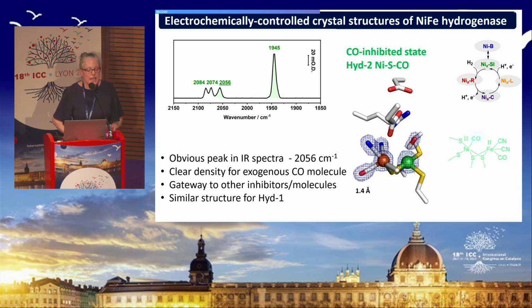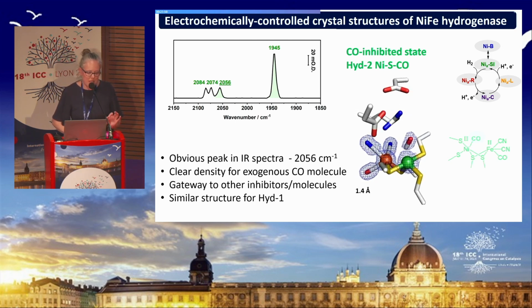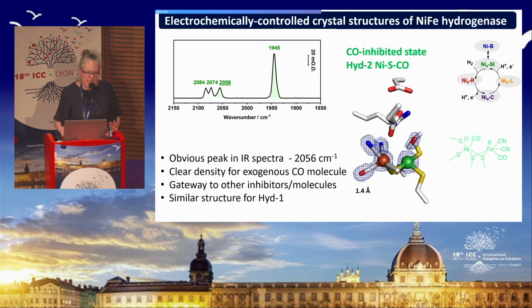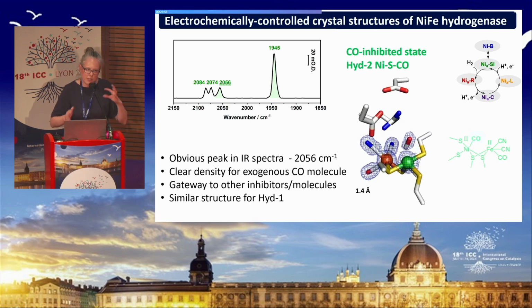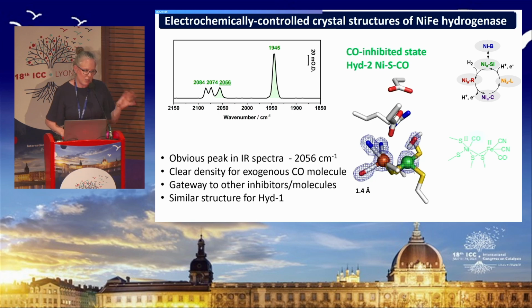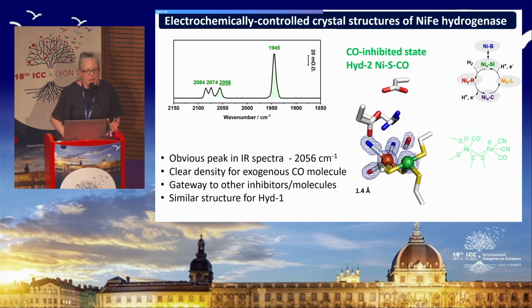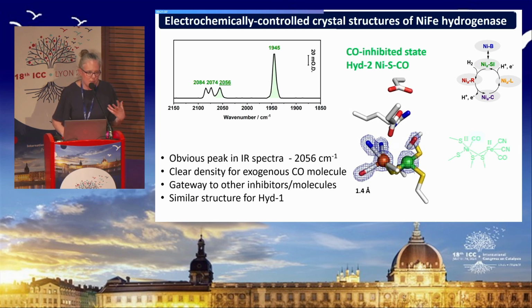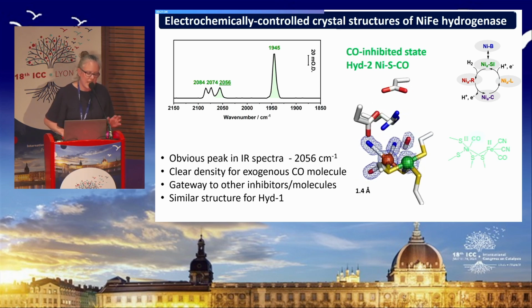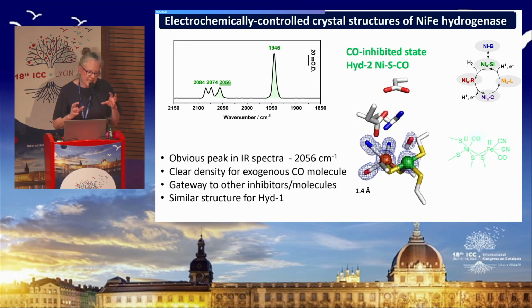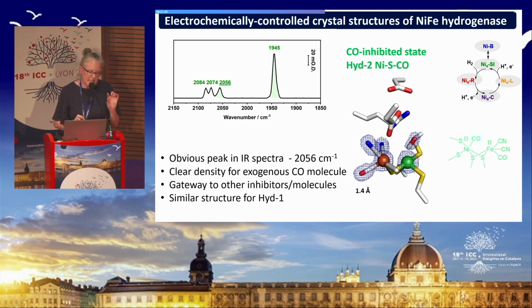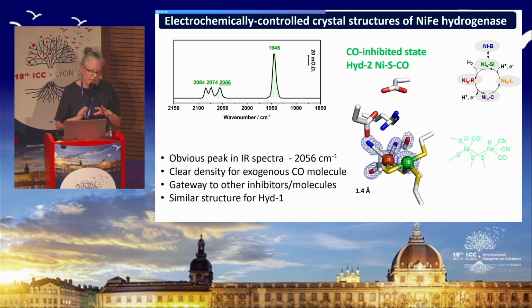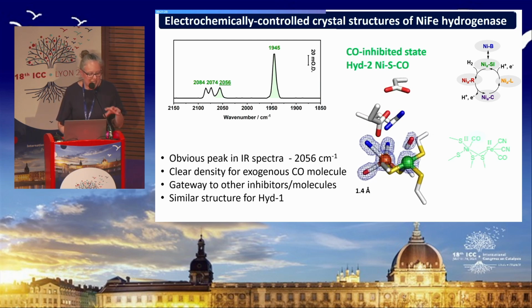This is all for an enzyme called hydrogenase 2 from E. coli, and I'm going to make use of 2 different E. coli enzymes in this mechanistic study because they have slightly different stabilities for different states in the active site, which allows us to get at different catalytic intermediates by choosing either Hyd-2 or Hyd-1. Interestingly, Hyd-1 has been thought to be almost completely insensitive to CO, like many other very oxygen-tolerant hydrogenases. But in fact, when we dial up the nickel Si state as a starting state and then react it with CO, we were also able to get a very similar structure for Hyd-1 completely inhibited by CO.